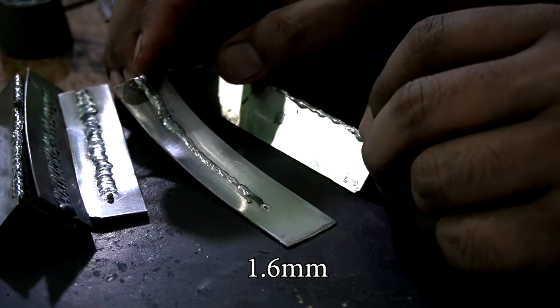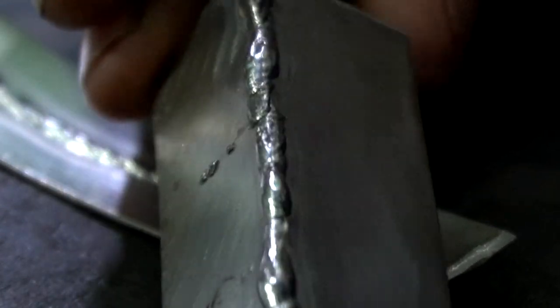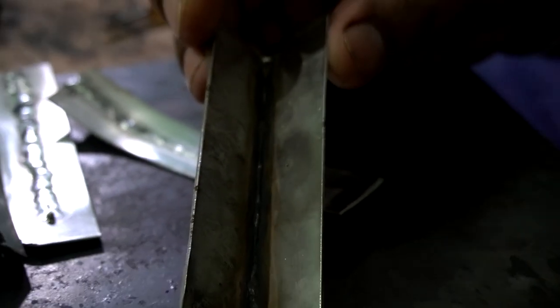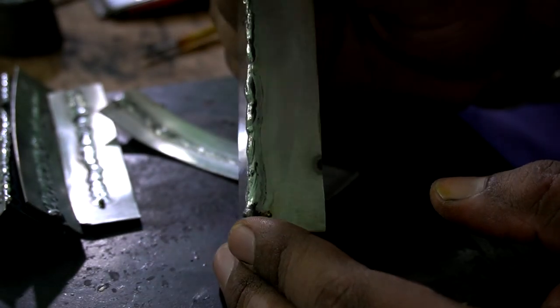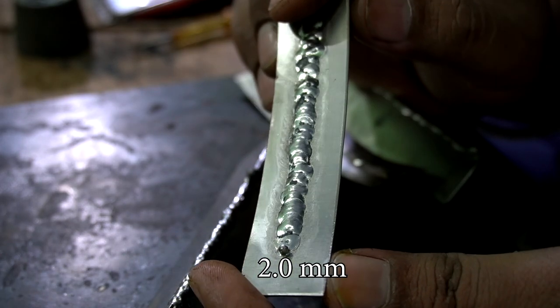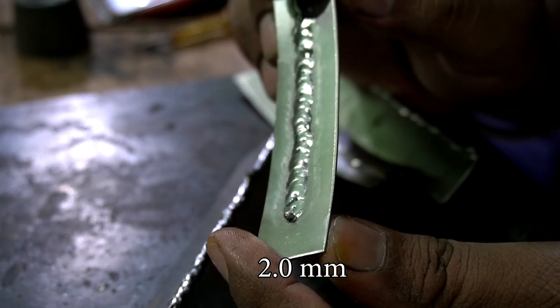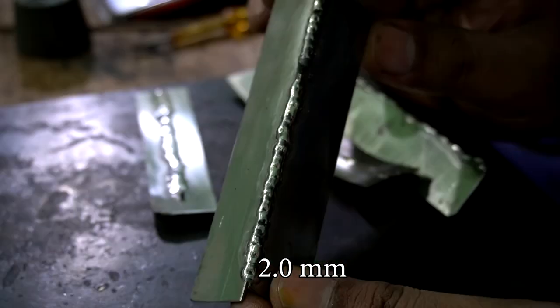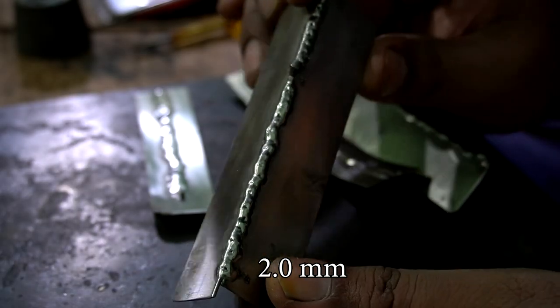So the thinnest bead I got with a 1.6 millimeter electrode, as the diameter says, and definitely there is no hole inside that workpiece, and also the metal got fused quite well. Even if I do the grinding work, there is enough material underneath which will be able to provide a nice smooth transition. This one I got with a 2 millimeter electrode, and I found it to be one of the best electrodes if you are willing to weld thin sheets like 18 or 20 gauge.